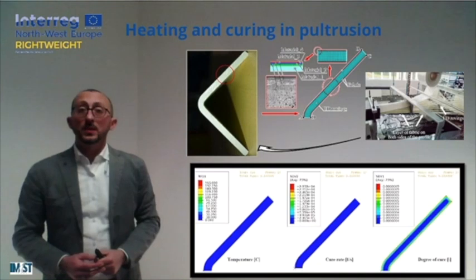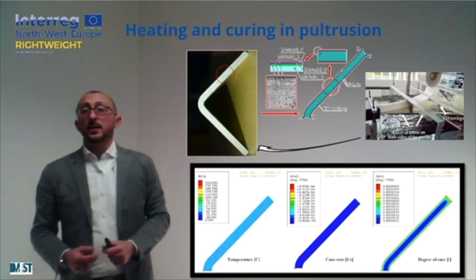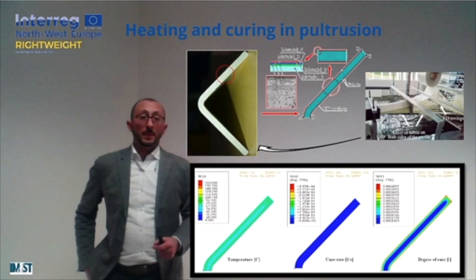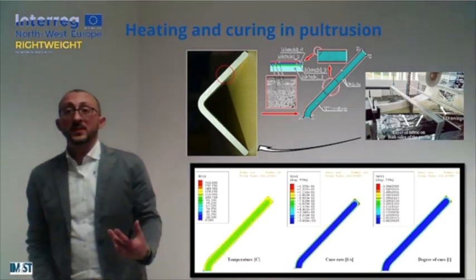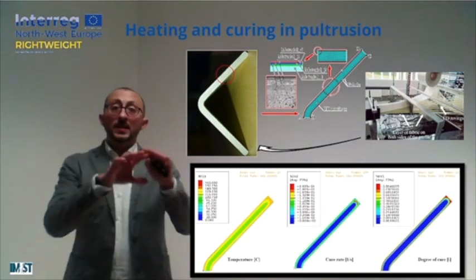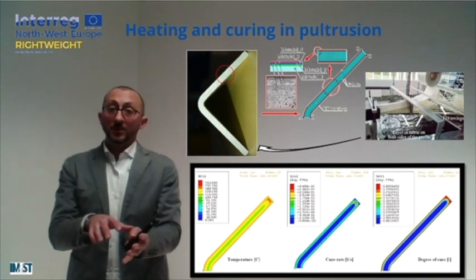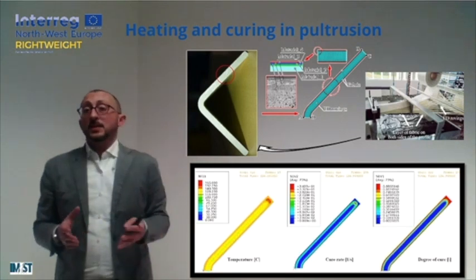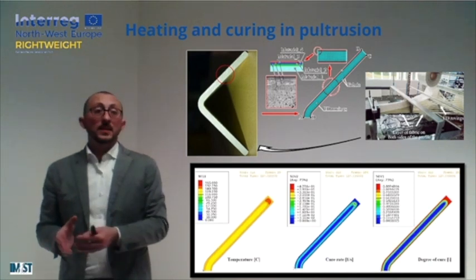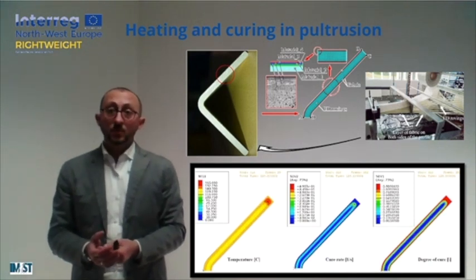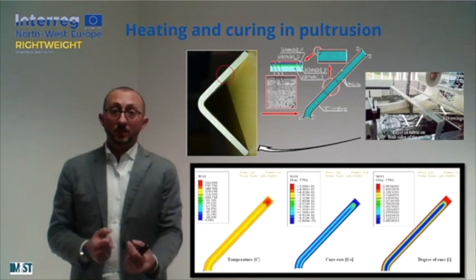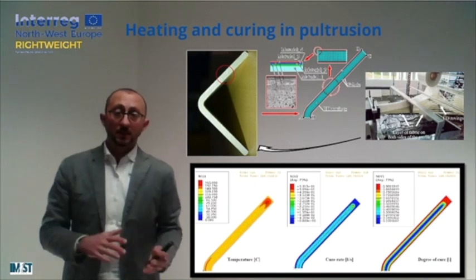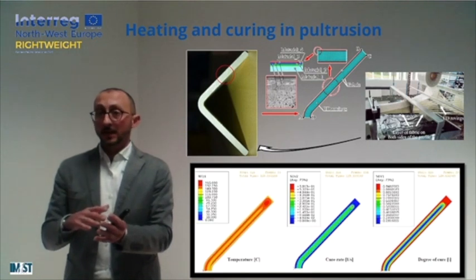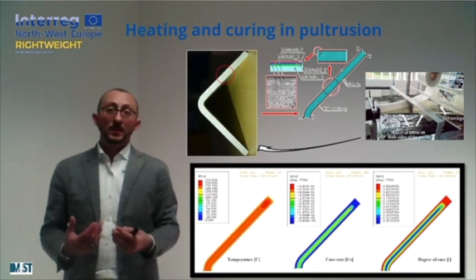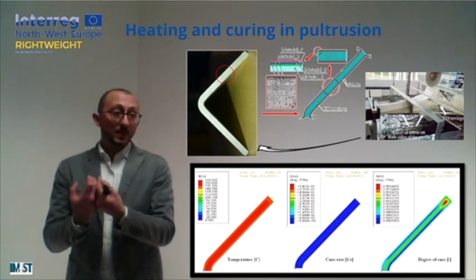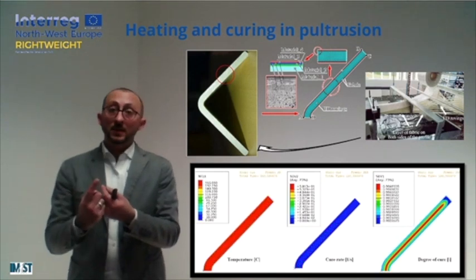And solving this problem, we can see that at the very beginning, most of the action is happening on the external surface of our composite. Basically, this is related to the fact that we are heating our material using heat conduction. So the surface of the composite is the closest part to the die, and it will be the first one that will experience this increase in temperature and the activation of the resin reaction.